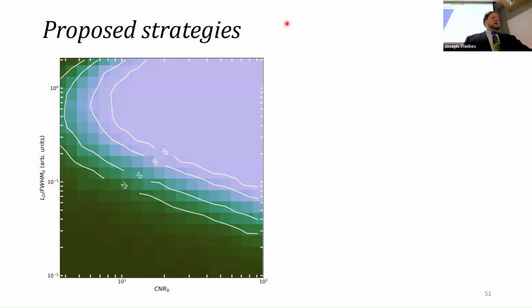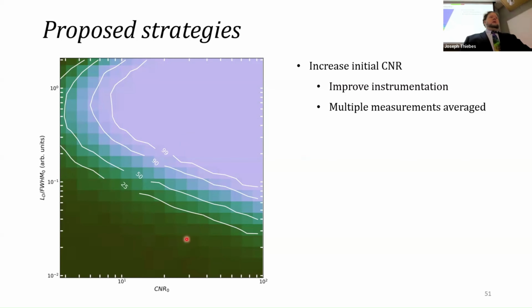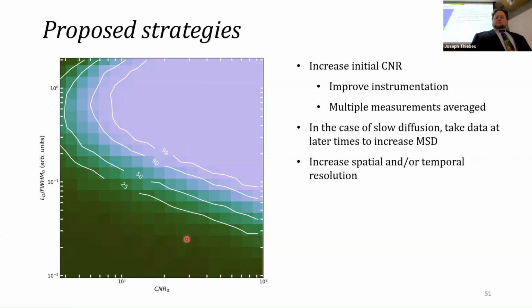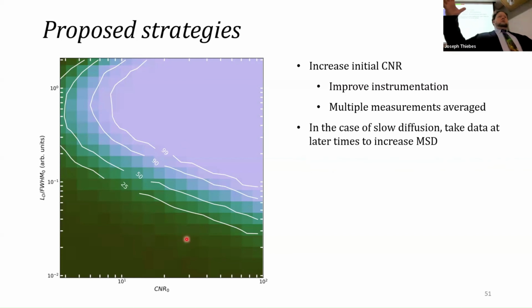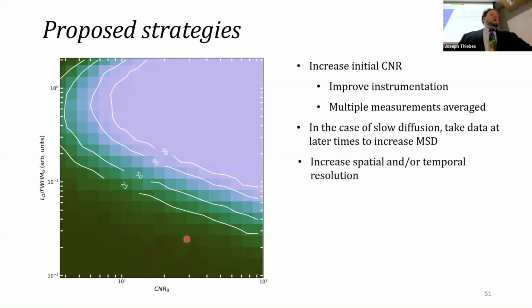So some other proposed strategies for folks if they find themselves in a situation where they're getting poor fits. Of course, you can increase your initial contrast to noise by improving instrumentation. Wouldn't that be nice? Or you can take multiple measurements and average the data in order to increase your contrast to noise. If you have slow diffusion, you can take data at later times to increase the total displacement. You can also increase your spatial or temporal resolution, although that doesn't improve a whole lot. It goes as root n.